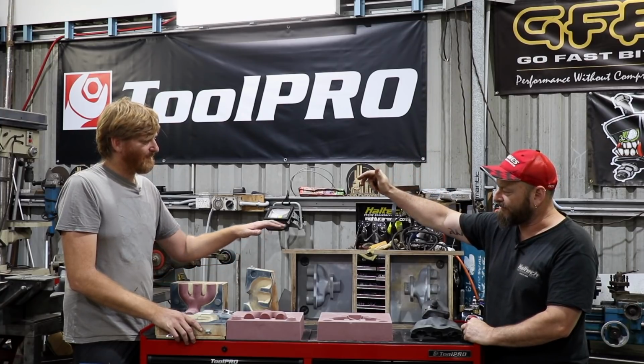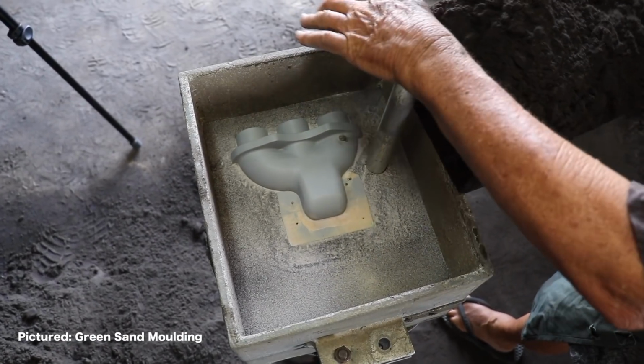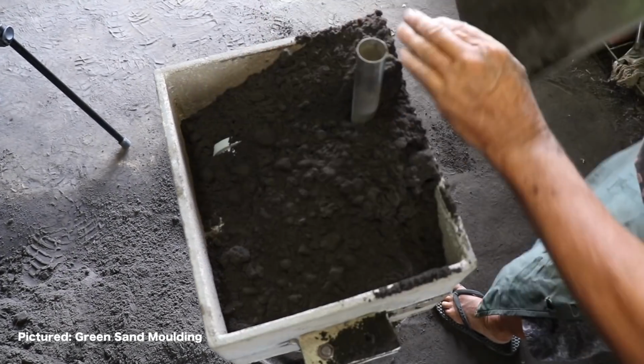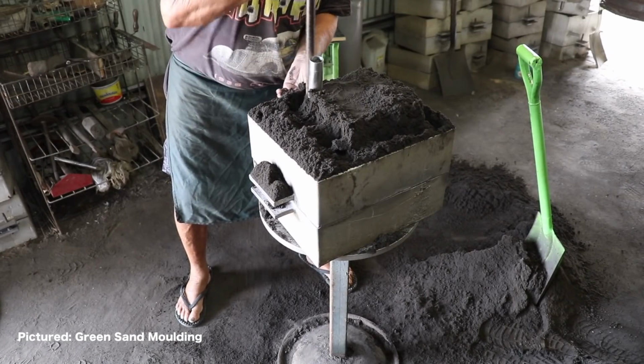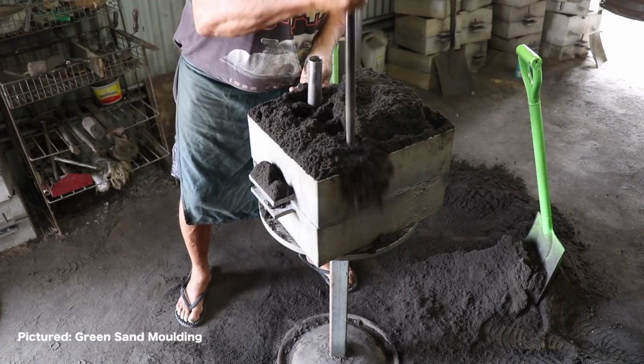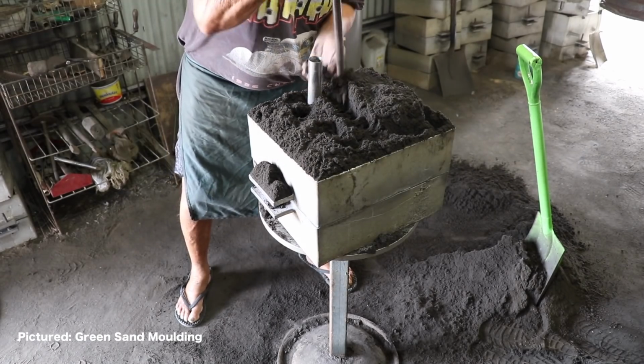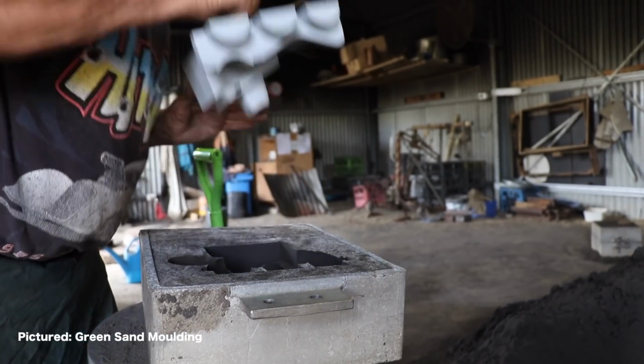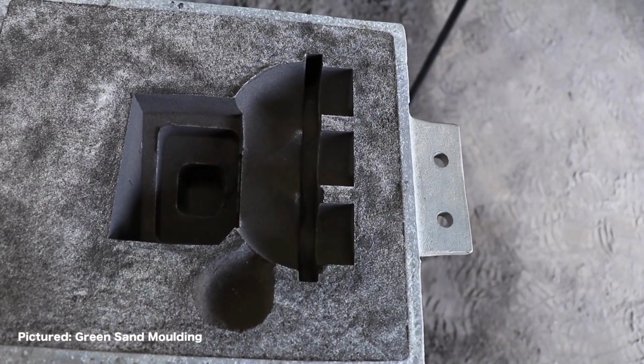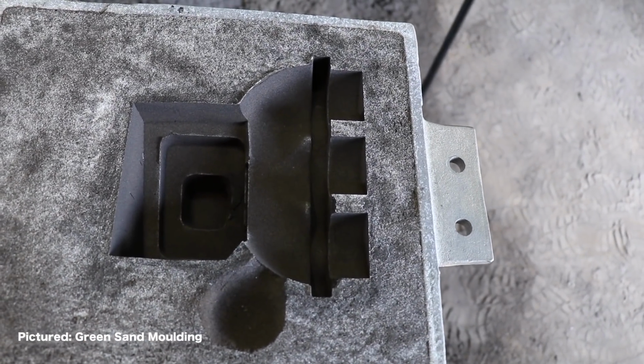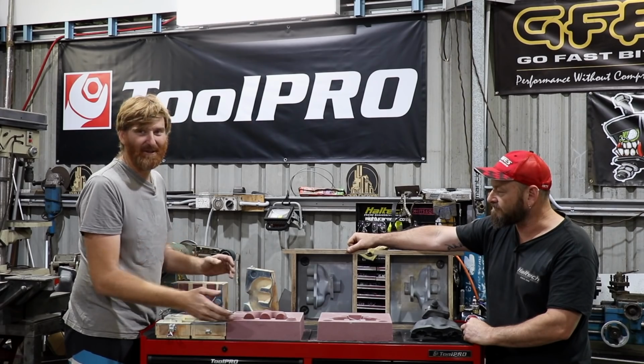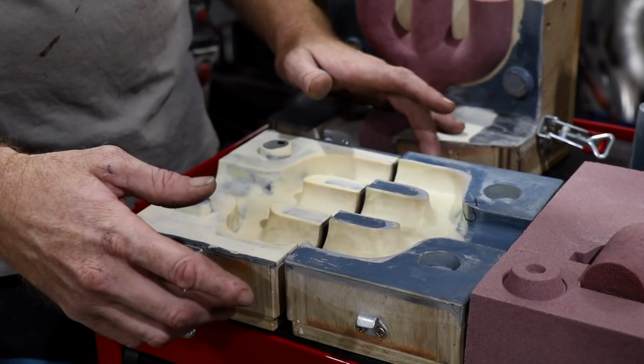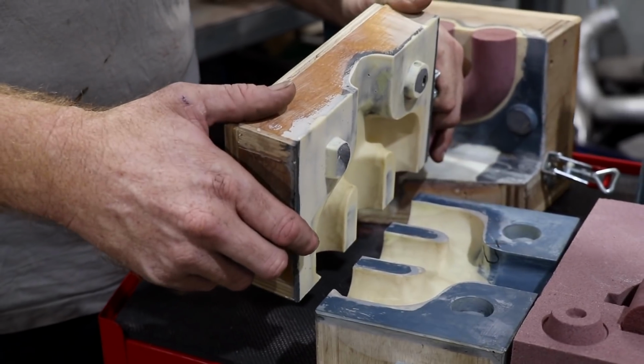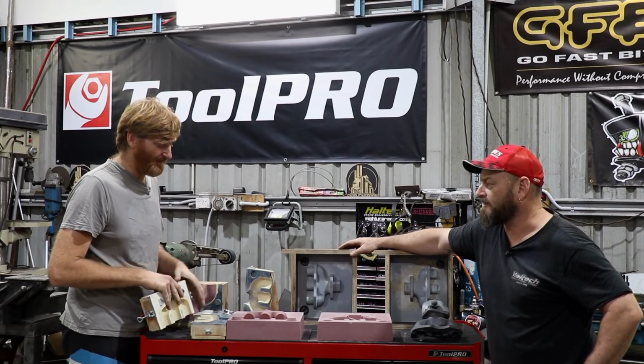All right. So next up, you basically fill these. You just fill the box up with sand. The sand's got a binder and catalyst in it. You don't pack these in too tight because you actually want the sand to breathe a little bit. So then you just let the sand set, about 15 minutes, and you can knock these out. You basically turn it upside down and tip the mould out. Same with the core box.